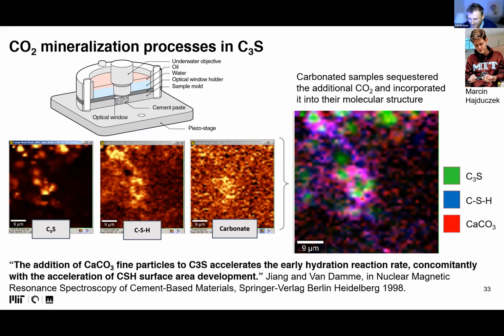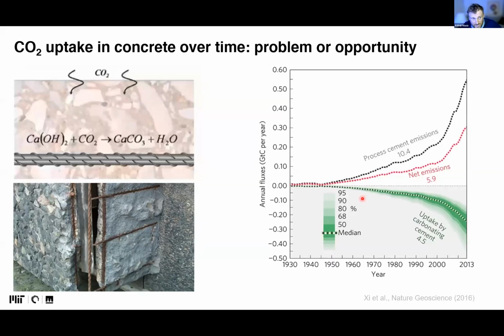I will return to cite my friend Van Damme, who published in 1998 that addition of very fine calcium carbonate particles accelerates the early hydration reaction rate. We see this also through many works that have recently appeared through pumping CO2 into fresh cement. But of course, we learned today also the other side of this medal, and how the CO2 will eventually play a role in degradation. Also, encouraging numbers from modeling are clear that there is a huge uptake by carbonating cement over the last 5 to 10 decades. So this is definitely something that we should look more closely into.